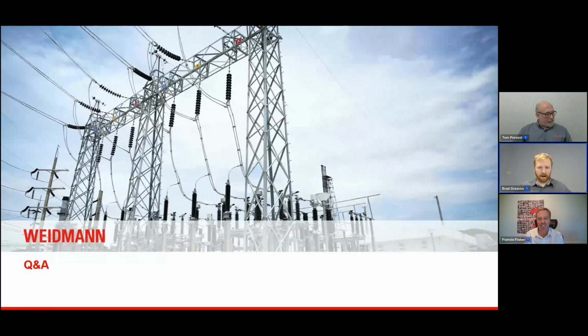Yeah, thank you, Frankie. So we did learn a lot in going through this process. Historically, these accelerated aging tests were focusing on the paper, so we didn't put a lot of attention onto the pressboard itself. In developing this test, moving to these larger vessels was a little bit of a challenge, determining the size that we really wanted, and how to prepare those in a different way. Still looking to achieve the same moisture content of less than 0.5% in the materials, and then drying out the oil as well.